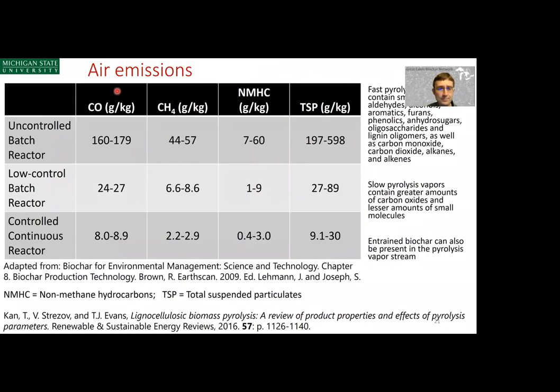So just considering the slow pyrolysis air emissions, in an uncontrolled batch reactor, you can see the emissions in terms of carbon monoxide, methane, non-methane hydrocarbons, and total suspended solids are greater than if you work with a controlled continuous reactor. The controlled continuous reactor emissions are quite a bit lower, and so your ability to control those emissions goes up with increasing automation. That's something to consider when it comes to regulating emissions and considering whether to practice at small scales or large scales.